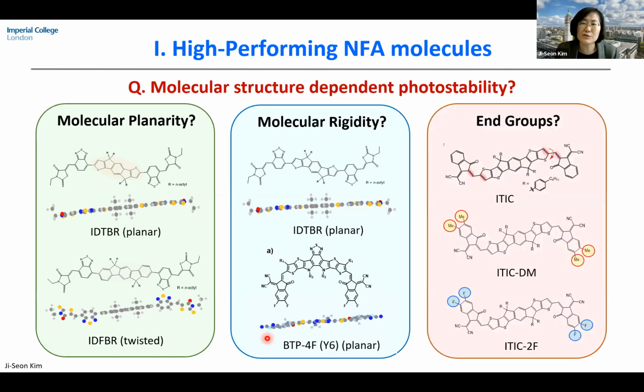And finally, you can actually change a lot of optoelectronic properties by putting in less or more electron-withdrawing end groups. So what's the impact of this end group on photostability? In order to look at this molecular structure dependent photostability, we consider the very fascinating molecular nature of organic semiconductors, meaning that when you excite, either by charge injection or photoexcitation, the molecule changes structure in order to adopt this excited state. So we use this molecular structure lattice change associated with photoexcitation in order to look at their stability.